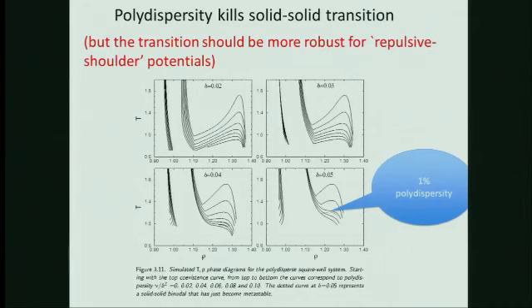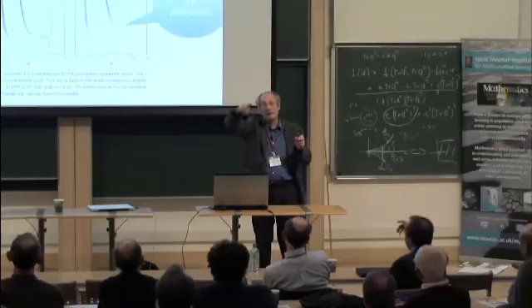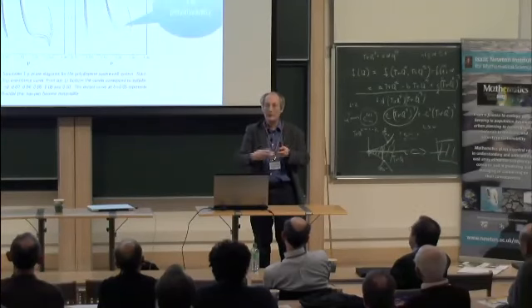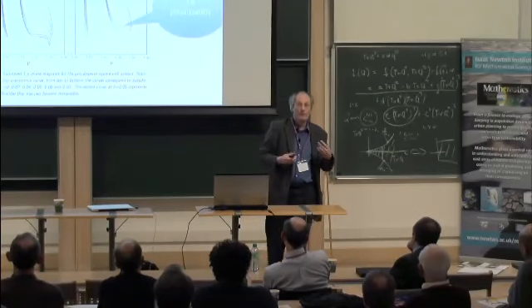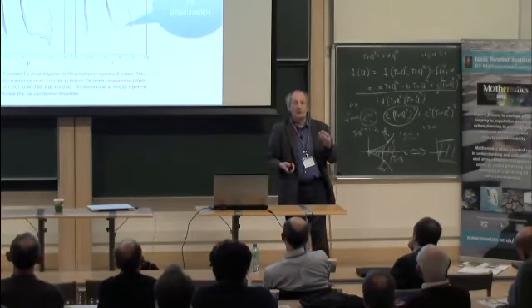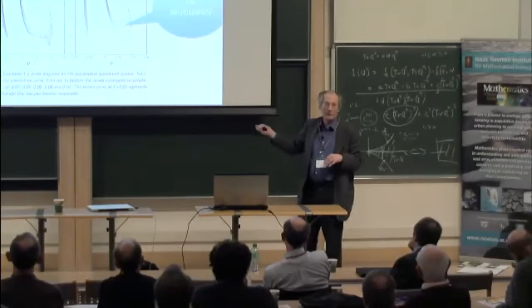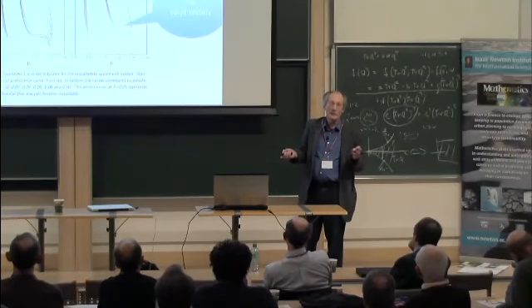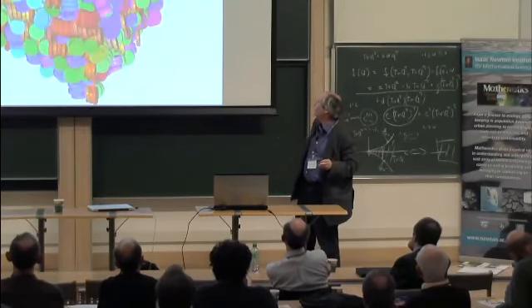Okay, other thing, this is for short range attraction. Actually, if you go for short range repulsion, that means a hardcore repulsion, and then a repulsive shoulder, maybe something you can do by putting some polymer brushes on the colloid, not too dense, then actually you make this transition more robust. That might be an easy route, hasn't been tried either.